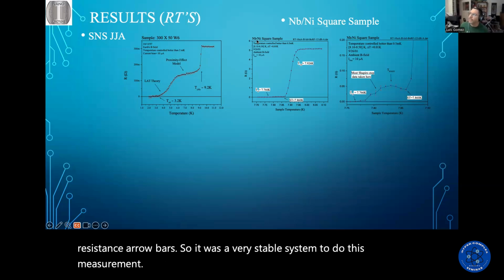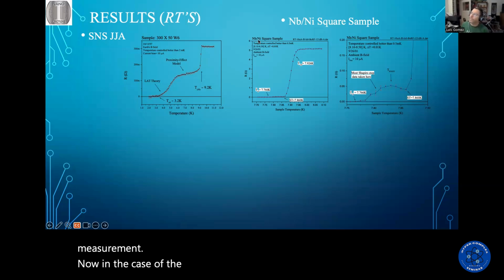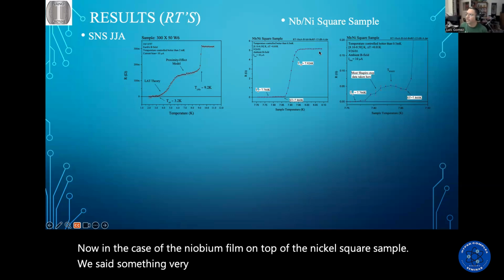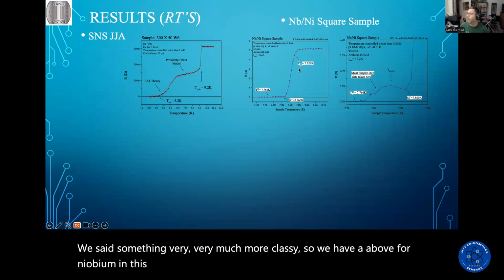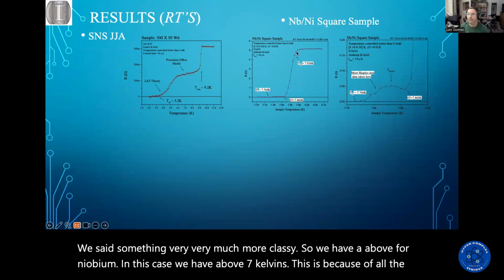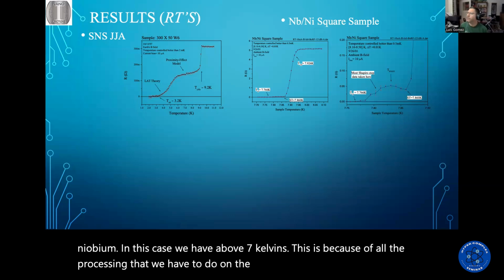Now, in the case of the niobium film on top of the nickel square sample, we see something very different, much more classic. So we have above 7 Kelvin for niobium. This is because of all the processing that we have to do on the system, so there is a reduction of critical temperature.